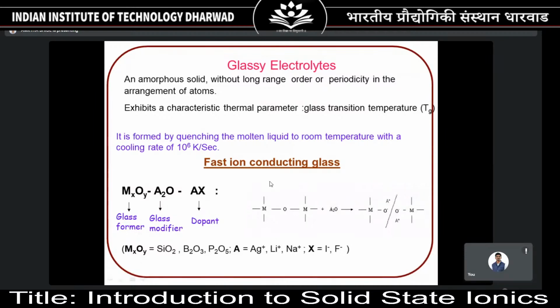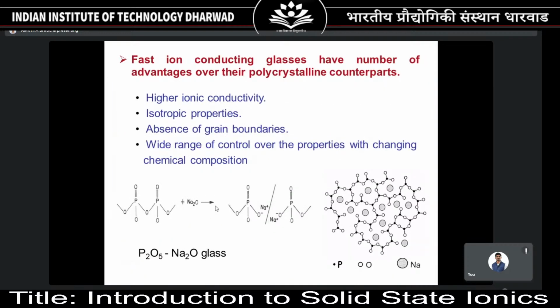Look at this reaction. A chained link of glass formers, MOM, which is getting interacted with glass modifier, typically oxides of alkali metals in our case, and they break the link, and these ions are free to move in the structure. And if you want to have further enhancement in conductivity, people also add dopants, where A again belongs to the alkali metal that you are looking for. For example, if you are looking for a lithium-ion conductor, I'll use a glass former like B2O3, and I use lithium oxide as glass modifier, and I take dopant as lithium sulfate or lithium iodide, for the further enhancement in conductivity. So this is what it looks like.